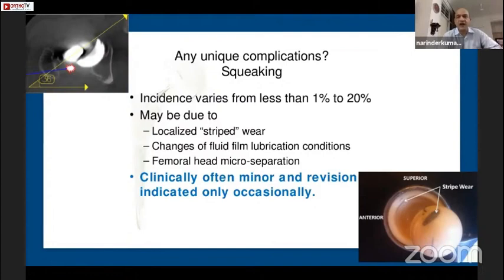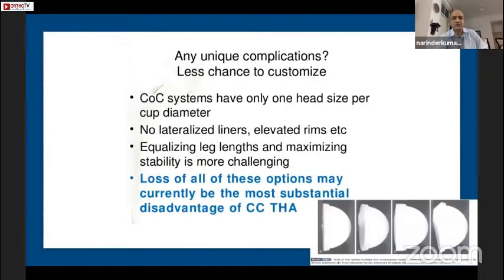Hard on hard bearings are very high demand surgeries. All the principles which were outlined in the planning of the surgery and in the cemented and uncemented components, which were highlighted by the previous speakers in sessions 1, 2, and 3, need to be followed very meticulously to have a perfect position of the acetabular component, as well as a good offset from the femoral side also, to avoid any striped wear which will lead to squeaking of the hips, because that changes a lot of biomechanical conditions there. But then clinically, these have now become fairly rare because we understand it now much, much better.